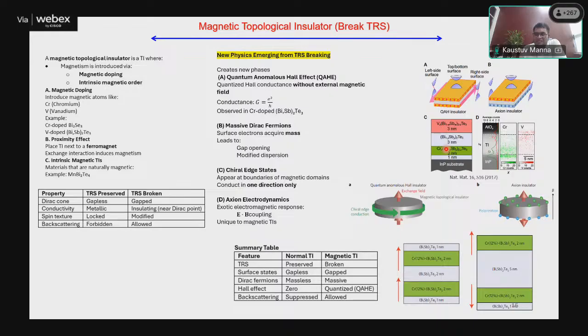Please look at this plot, the right hand side. You have a topological insulator. When you have a topological insulator without any magnetic doping, without any proximity effect, you get the edge states. But if you apply the magnetic field and align these ferromagnetic layers in one direction, you induce a proximity effect, because of the exchange interaction. So only the up spin will be protected, but the down spin will be gapped out, because the down spin with respect to the up spin of this ferromagnet will simply annihilate. The moment it gaps out, it induces a Berry curvature hotspot. Because of that Berry curvature hotspot, the electrons which were in that channel add up in the existing channel because of the spin momentum locking, as I have explained here.